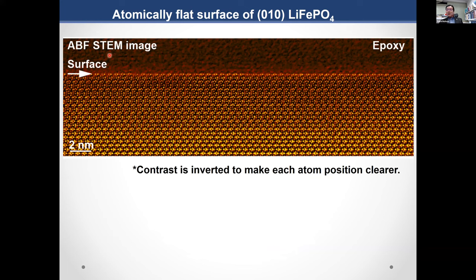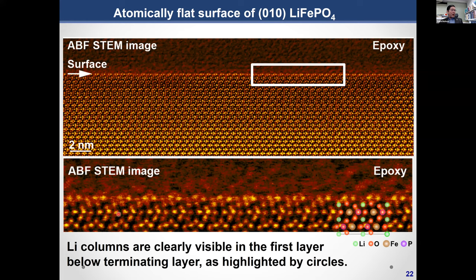Therefore, this is an ABF image, not a HAADF image. So you can see the surface very clearly, and we magnified this region. This is a magnified image. You can see the relaxed structure. That is, surface relaxation actually occurs. So you can see this one.